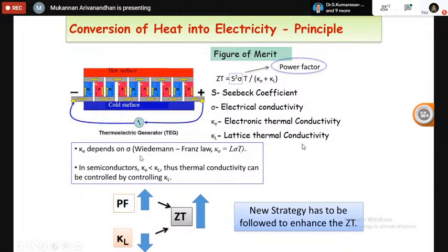But the thing is that the Wiedemann-Franz law is valid only for a high electron density material, like metallic material. Whereas if you choose a low carrier density material, like semiconductor material, then the electronic part of thermal conductivity is quite low compared to the lattice part of thermal conductivity. So by properly engineering the semiconductor with the appropriate carrier density, you can prepare a material with low carrier concentration. Then you can have the dominant lattice thermal conductivity compared to the electronic part. Another important piece of information is that the lattice part of thermal conductivity is no longer related to the electrical conductivity.